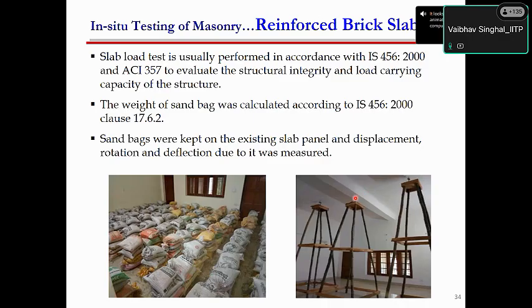You have to load the slab in small loading intervals, and keep on noting the deformations. After 100% of loading, leave the load for 24 hours, and then you start unloading. After unloading, you have to see how much of the displacement noted during the full load has been recovered. The code says that if 80% displacement is recovered, the slab is a good slab, meeting the acceptability criteria. So these are the various tests you can do to evaluate the strength of your existing building.